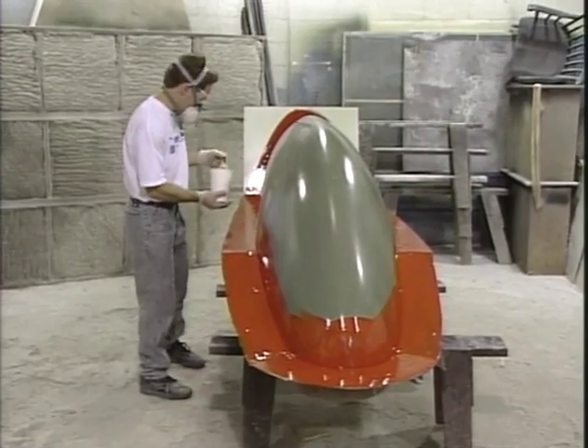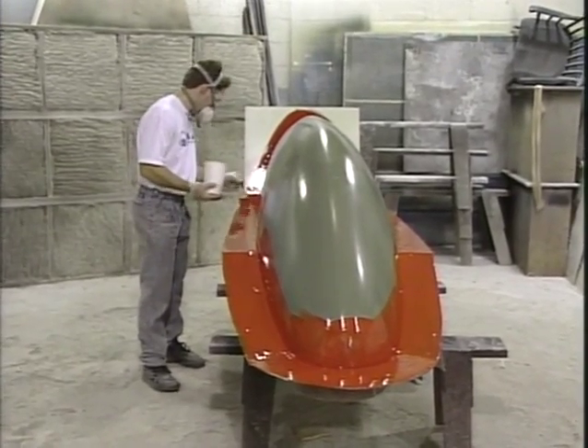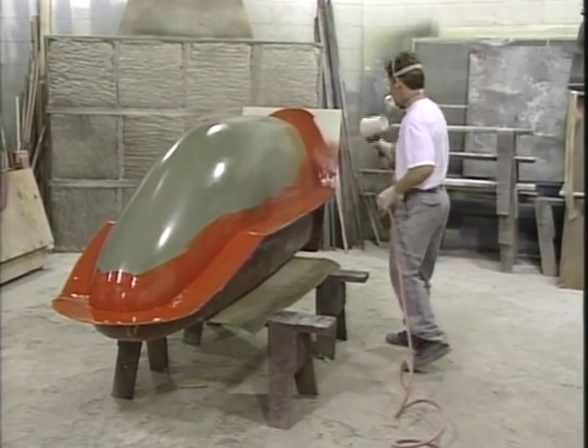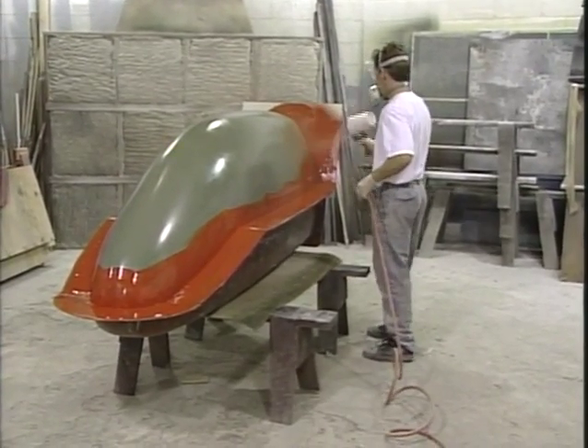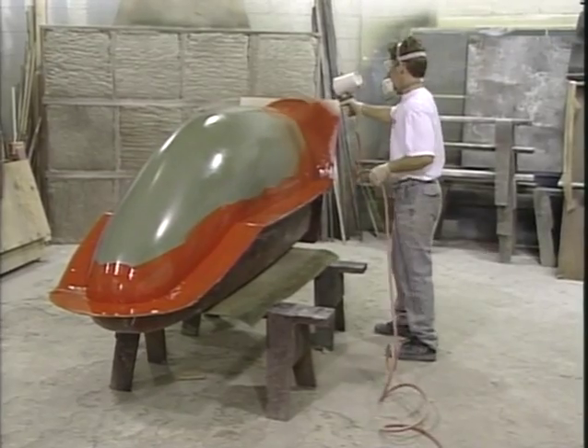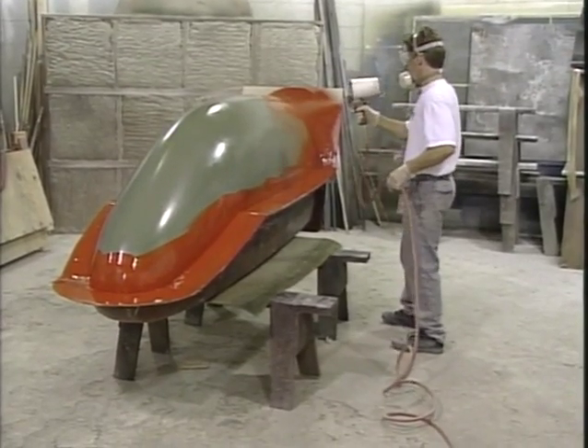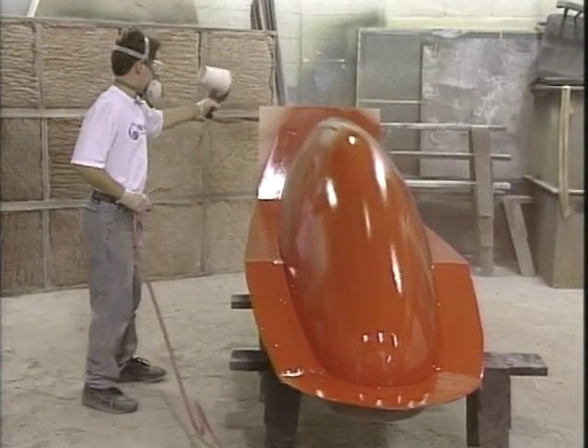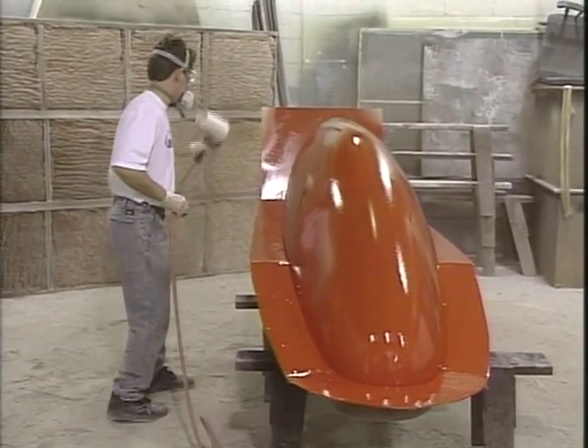After the flange was covered, I was ready to spray gel coat over the entire surface of the mold. Using the gel coat cup gun, the remainder of the coat was sprayed on. The brush strokes quickly disappeared when covered with the atomized gel coat. Gel coat is sprayed rather than brushed whenever possible. Even an experienced person will have occasional trouble with gel coat. Gel coat problems are usually a result of spraying too thick. Several thin passes are recommended.